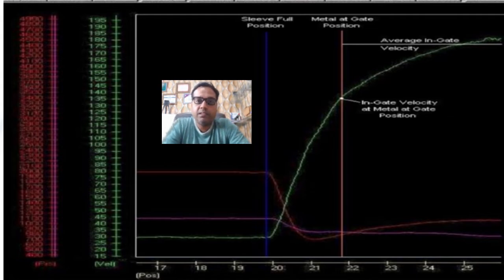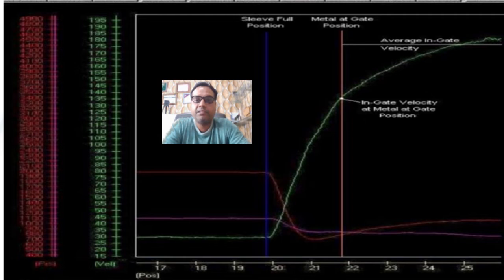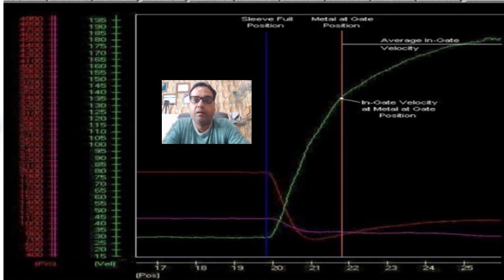Another process variable during cavity fill is in-gate velocity at metal at gate position. This value should be at least as high as the average in-gate velocity to assure that cavity fill will begin with an in-gate velocity that provides proper initial atomization when metal first travels through the in-gate. If the in-gate velocity at the metal at gate position is below the desired value, the atomization during fill may be compromised. If a problem occurs, the first rod start position may be starting too late or the slow-to-fast acceleration is too slow.